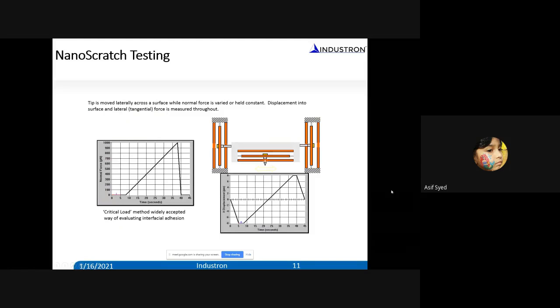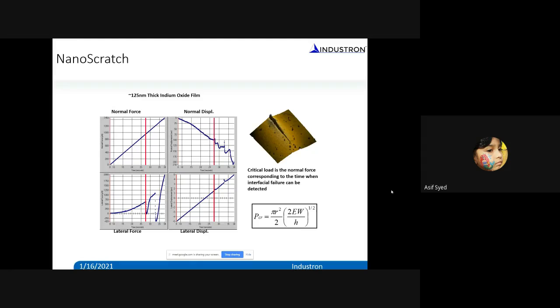Okay. So now we can extend this to, for example, if you are interested in tribology, you can do that by adding another transducer on the lateral side and sliding the transducer, applying the normal load and doing a scratch test. At the same time, you can apply a normal load and measure the normal displacement. Along with that, you can also apply lateral force and measure the lateral displacement.